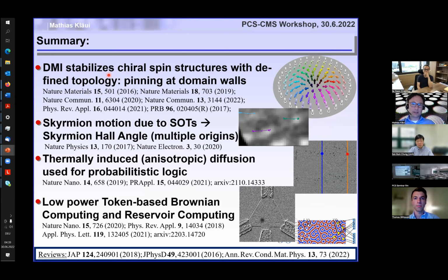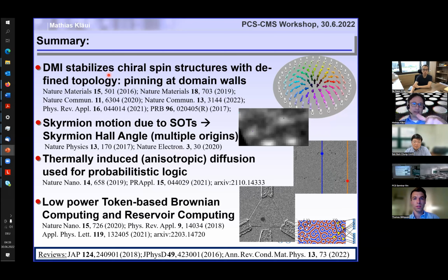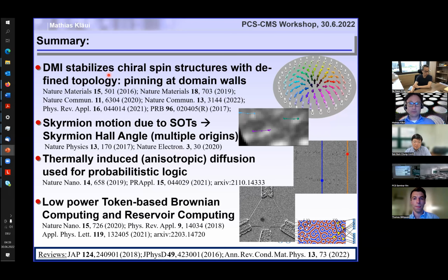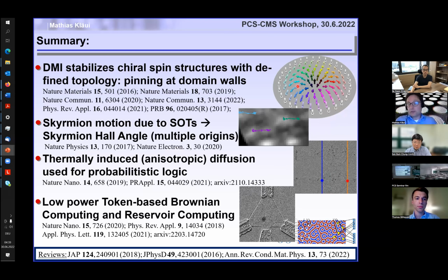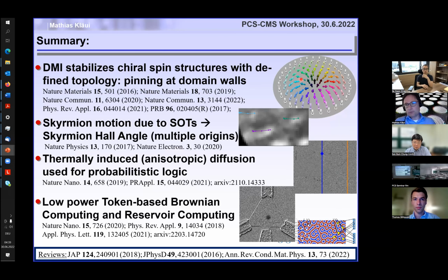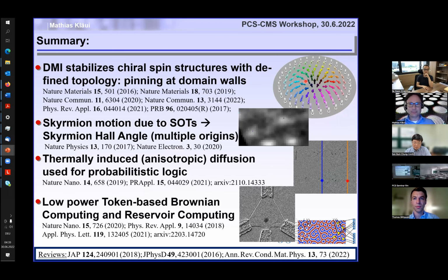Another option is you can measure domain wall motion because if you have Dzyaloshinskii-Moriya interaction, you will favor Néel walls, and by applying in-plane fields, you can tune between Néel and Bloch walls, and you can measure that. You can directly image the domain wall spin structure. So there are a range of different approaches that you can use depending on the system and your availability of certain measurement equipment in the lab. If you send me an email, I'm happy to send you a slide where I have an overview of all the different methods of how to measure it. Okay, sure, I will do that.